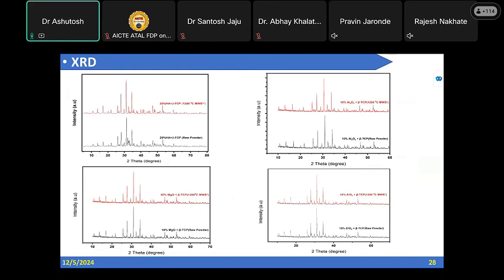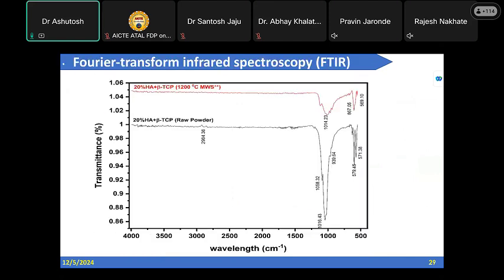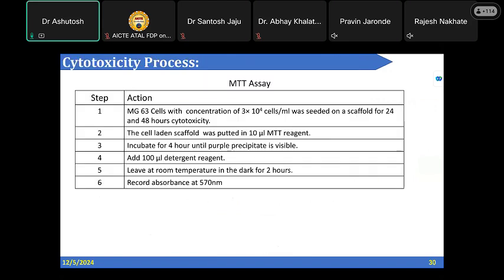This is the XRD data of all three of my cases. If you see the raw powder and the powder sintered up to 1200°C, they have the same values. This is the FTIR data, which shows that even after the post-processing we are not getting any new kind of bond formation, which means the material before the printing and after the printing and post-processing is the same. So it is safe to use.